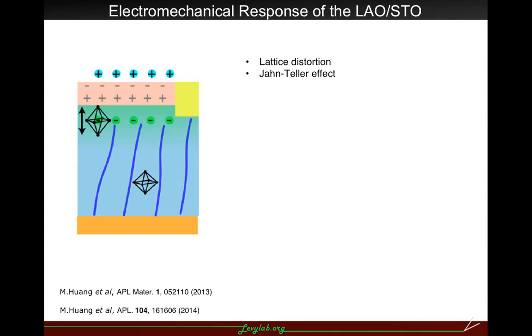At the same time, the other aspect of the LAO-STO heterostructure, the electromechanical response, has also been studied. First, first-principles calculation has shown that the lattice distortion and the metal-insulator transition have a connection. The lattice distortion is observed in the STO near the interface by using transmission electron microscopy. The lattice distortion is carrier density related due to the Jahn-Teller effect. When charge accumulates at the interface, titanium 4+ will become titanium 3+, and this will cause the elongation of the octahedra and lead to the distortion of the interface.